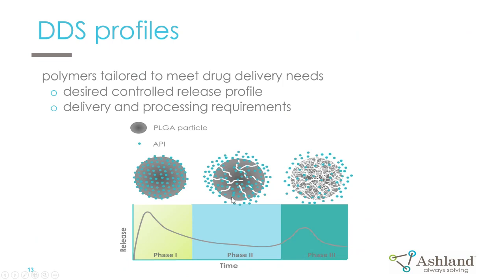So as the polymer takes on water, starts to swell, it will form pores. These pores will get larger over time and diffusion will occur. So drug will be diffused from the matrix outward and be released. And this is typically the longest phase of release. And finally, a third broad phase of release, which is very often not present. So if you think about this, the polymer over time in the body, let's say over weeks and months perhaps, is losing length in terms of chain length. It's losing molecular weight. So as it gets shorter and shorter based on hydrolysis, the molecular weight will reach a critical low. So at that critical low point, it will start to occur in form of mass loss. So it would crumble. And if that depot crumbles, any drug that would be remaining would finally be released.